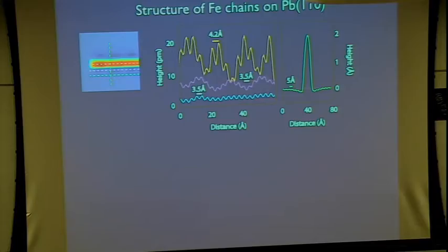Lead actually doesn't fit with iron. They have different lattice structures. So of course it looks beautiful when you look at it from far away. But if you zoom in, you start to see picometer modulations on top of the structure of this chain. And if you go nearby, you see even the lead. I don't know if this is coming out or not. This is a cut taken this way. You can see that it sort of strains the lead to fit in.